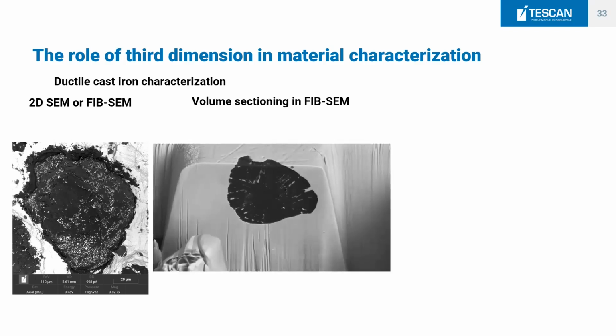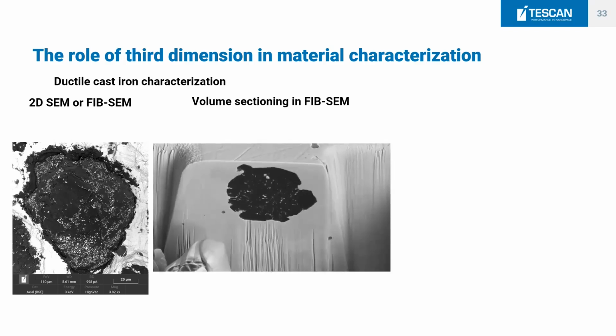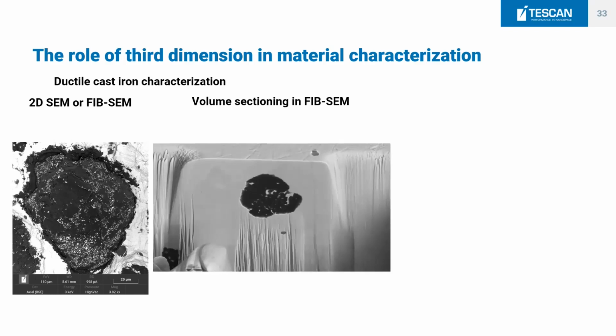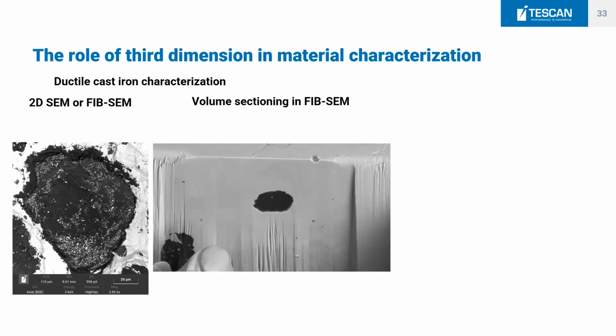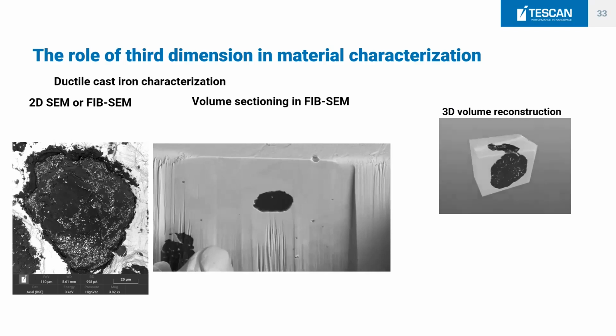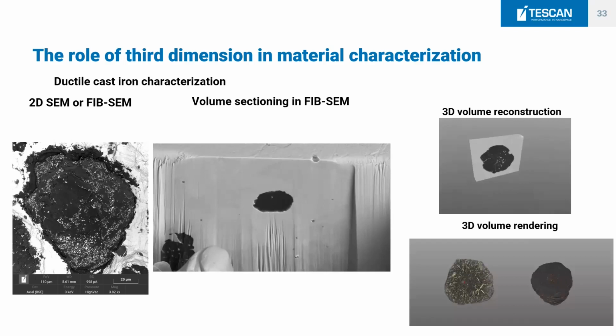So what you could do more, you can continue to slice and view, or you can slice a thin slice and acquire an image. And you can take this data set and reconstruct the whole nodule. And you get this 3D volume reconstruction. And you can really see what the internal structure of such a nodule looks like and where the initiation point of this nodule is and how the growth has been driven when the material was developed. So all of that is the complexity which I was talking about earlier. So it's not only about imaging, but at this point, we are really talking about a complex description of a very small feature.